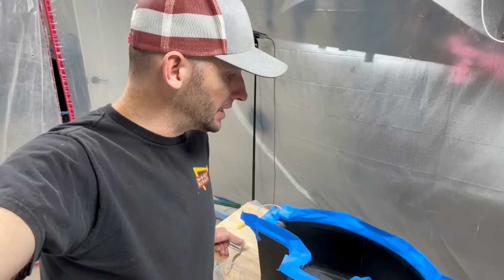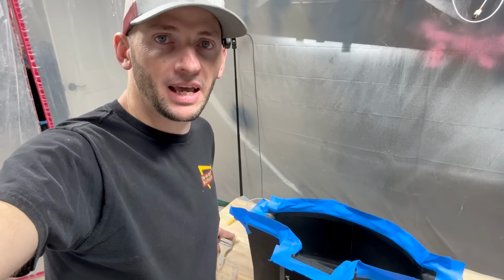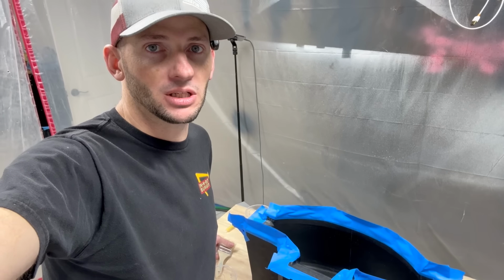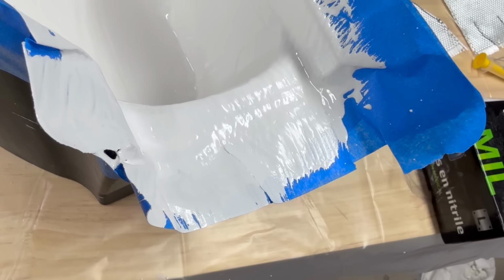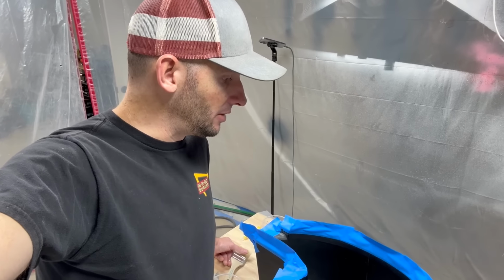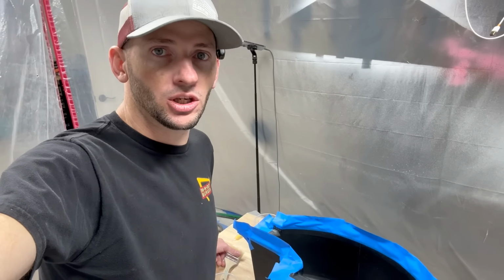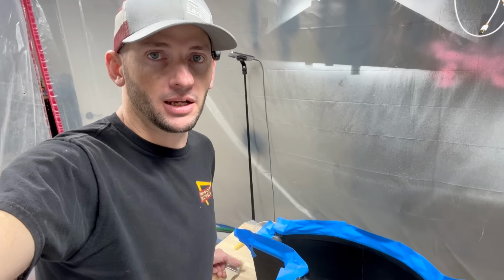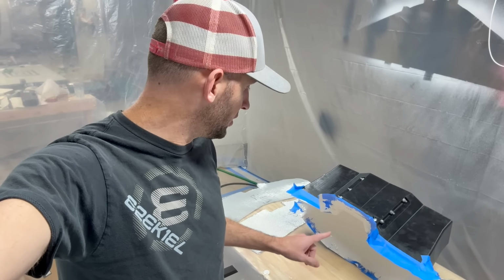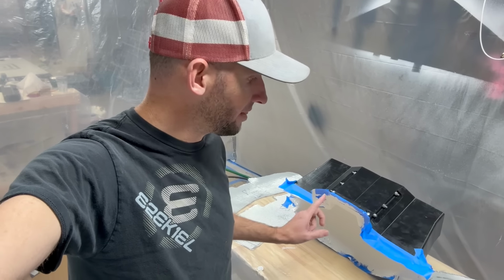We're going to go ahead and lay down 2 layers of gel coat, let that tack off, basically so you can touch it with your glove and it doesn't remove any material. And then once that second coat is mostly cured, we'll continue on with the fiberglass. All right, the second coat of gel coat is in. We're gonna go ahead and let that tack up.